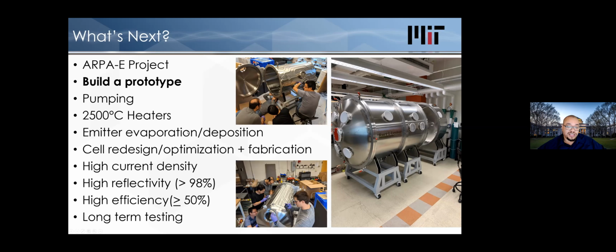This is the point I made about tungsten acting as a mass barrier for carbon deposition. We're working on cell redesign and optimization and fabrication. Got very high current densities, so there's a lot of integration challenges with actually getting the current out of the cells. So imagine a little square centimeter cell that's got 10 amps coming out of it. All right, so you got to touch it with some rather large wires. So there's a lot of integration challenges with doing that. And we're working on building a full-scale prototype that will fit inside this vacuum chamber. So this is about a 10-foot long, 5-foot in diameter vacuum chamber that we have in my lab. So we keep the entire system in an argon environment.